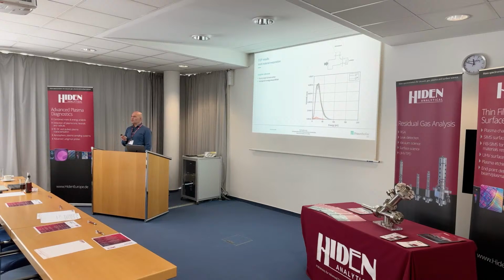First, we did some initial measurements of our graphite electrode, the cathode, which we evaporated with the process, the pulse form I showed you before, the 1600 amps rectangle pulse. And here we have the ion energy in electron volts for C plus and C2 plus, and of course we know we have mostly C plus and only a little C2 plus. There are also thermal effects of our graphite cathode. If the cathode is very cold in the beginning, we get a larger amount of C2 plus, but as it gets hotter and hotter, it gets less and less. So we always did some initial running in of the cathode so that it gains temperature, and measured after this.